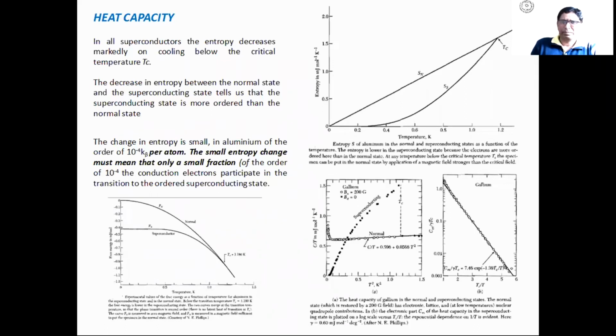But it is also observed that the change in entropy is very small. For aluminum, the change in entropy is only of the order of 10 raised to power minus 4 k_B per atom. We could expect 1 k_B for one electron, but here it comes to be 10 raised to power minus 4 k_B per atom. This small change means that very few electrons are taking part in the superconducting state. Not all electrons participate in making the material superconducting.